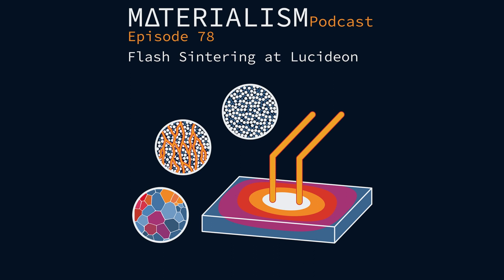I've never done flash sintering, so this is interesting to learn about, but I'm surprised that you can actually raster it. I would have assumed naively that if you sinter part of it and then pass over next to it, you're really hoping against hope that these ceramics will densify in the same way so that you won't get cracking along those interfaces. Do you tend to get cracking along the pathway of the raster?